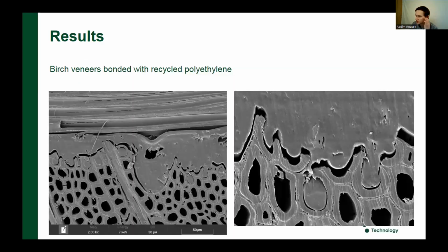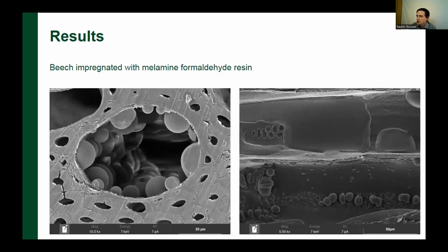Another example is birch veneer bonded with recycled polyethylene. You can see the bond between polyethylene and birch wood is simply just interlocking. There is no real adhesion between these two materials. And this is beech impregnated with melamine formaldehyde resin. This resin is very strong, very hard, and difficult to cut with microtome or razor blade. It makes the blade wear out very quickly.